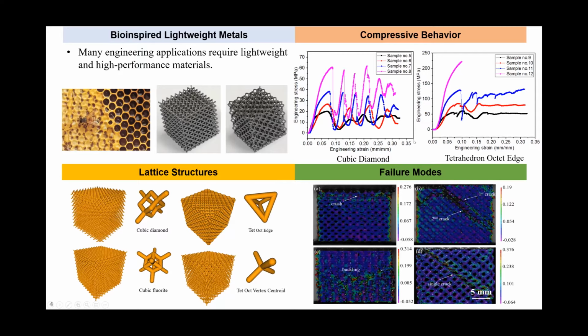So in other words, by varying the relative density of the lattice structure, as well as varying the unit cell type, we can tune or tailor the compressive behavior. And in this case, you can see they exhibit very different compressive strengths if you take a close look at the engineering stress. And also, we further observed the failure modes of these different lattice structures. Actually, they exhibit very different failure modes as well.